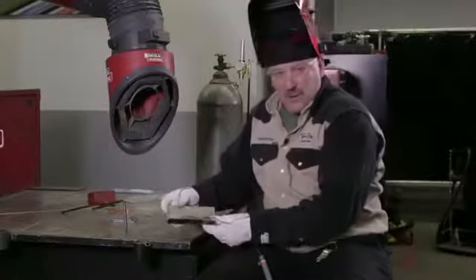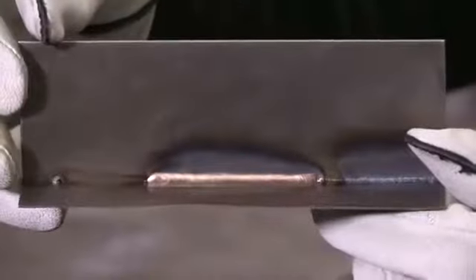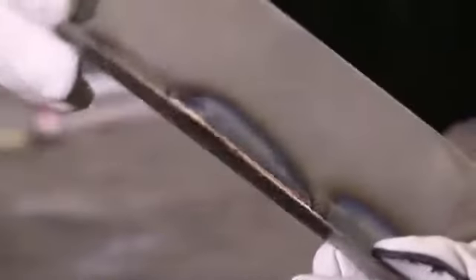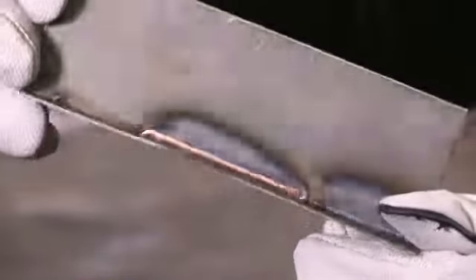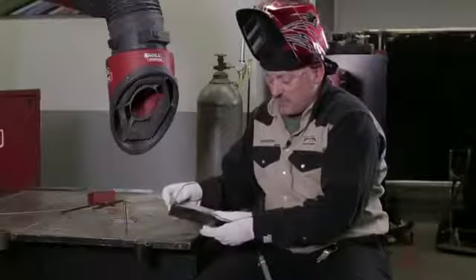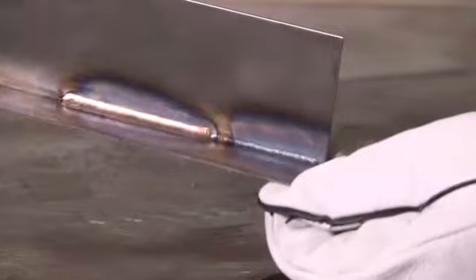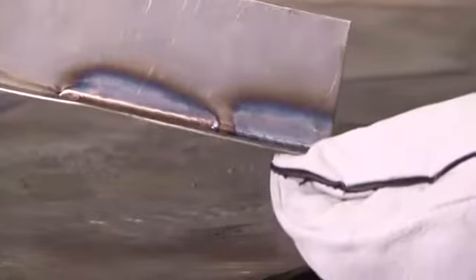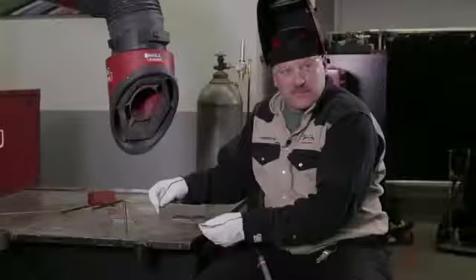You can see we have a gold looking weld there. Little bigger leg size on the weld. This material is not quite as strong as steel, so we're not really welding. It's really kind of a brazed joint, brazed welded joint. But you see here we don't have the damage or the burn through on the back side. Little less heat input because we traveled a little faster even though I ran more current. So sometimes that's used to limit distortion on jobs because you can run lower current.